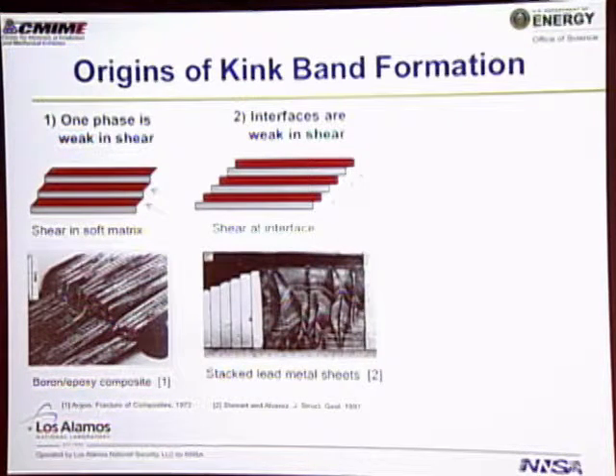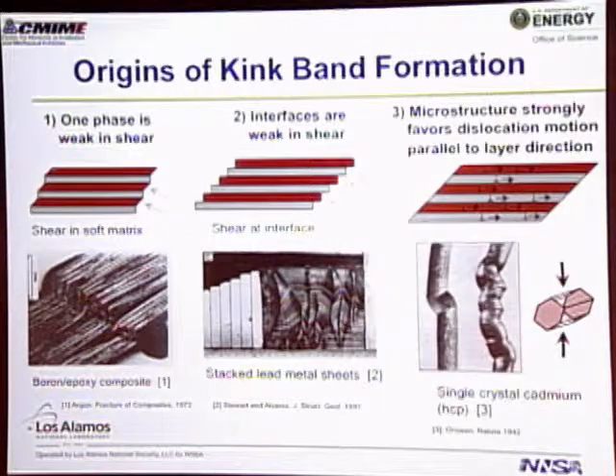The geologists have done this with stacked lead metal sheets. So you originally stack them this way, and you compress this. And you can also see kink bands in this case. In our case, it's probably closer to what Orowan, one of the other founding fathers of material science, found in 1942, where he tested single crystals of what's called a hexagonal close-packed material, in this case cadmium, and what he found is that he saw these here as well.